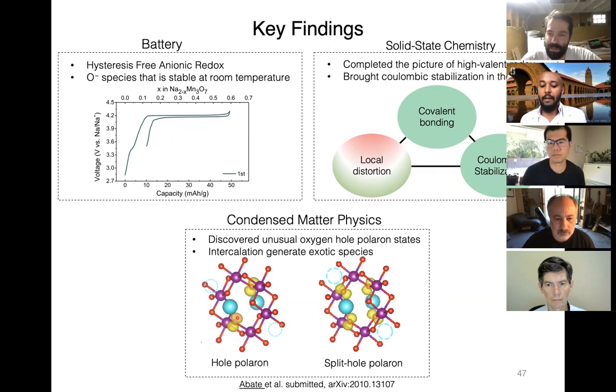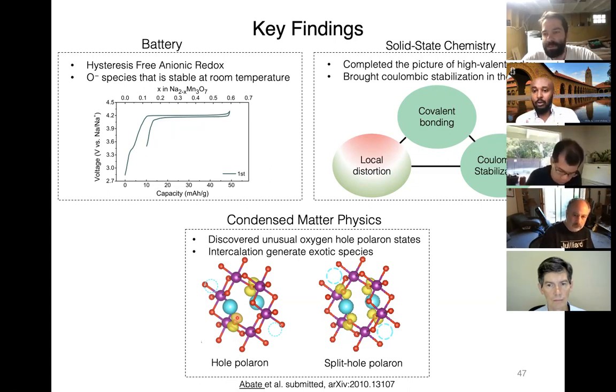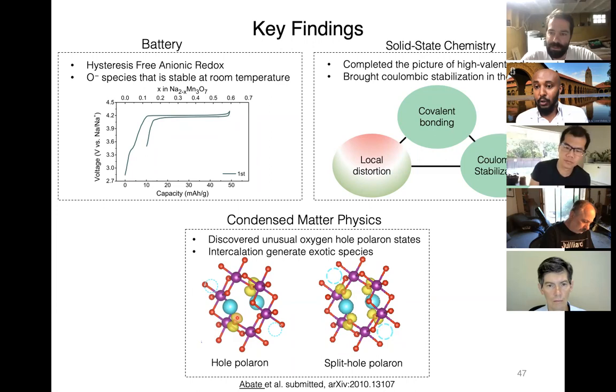I think, for example, if you're able to design electrolyte systems that still work at high voltage, I don't see an issue where this could still be relevant in terms of catalytic application, where they won't be suppressed by surface reactions. But the work we have done so far is trying to avoid those, either through the electrolyte or the voltage window, but also being careful about the surface of the material to clearly observe this species. So a good way to answer your question, and something we are trying to learn and discuss right now, is how can we also coat the surface of the materials, therefore avoiding surface reactions that could ultimately affect the property of the bulk material we are observing. With our understanding, surface coating and electrolyte design, what you asked about could be possible, and we can achieve that without those issues.